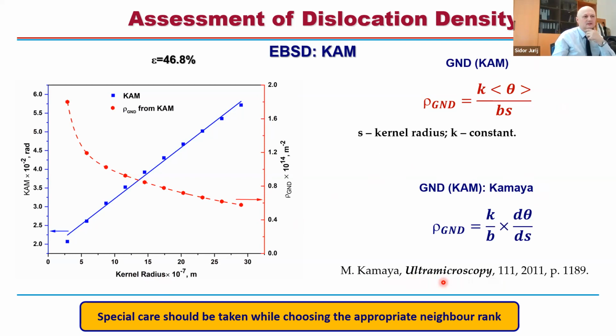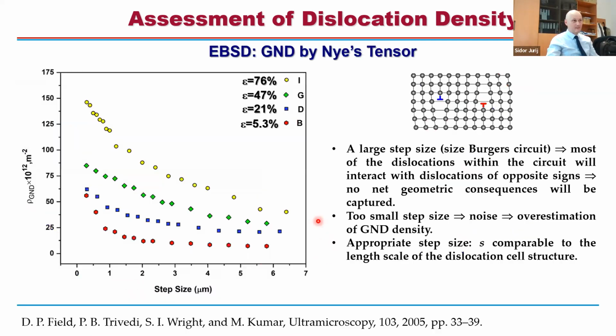published a work in Ultramicroscopy, and what was shown is that, in fact, instead of putting in misorientation, some average misorientation, you put basically this slope, d theta by ds. Basically, you put the slope of, normally, a straight line. And if you put this slope, then you get a more reliable answer about the geometrically necessary dislocations. So special care should be taken while choosing the appropriate neighbor rank or kernel radius.